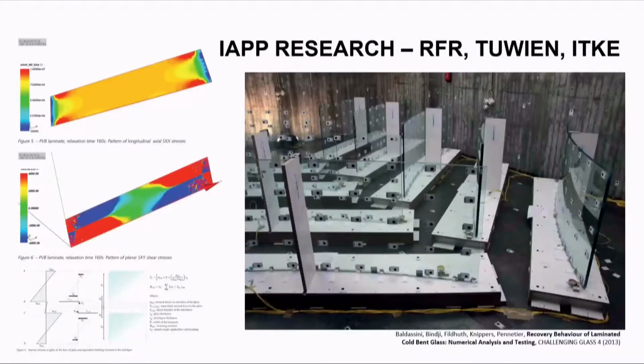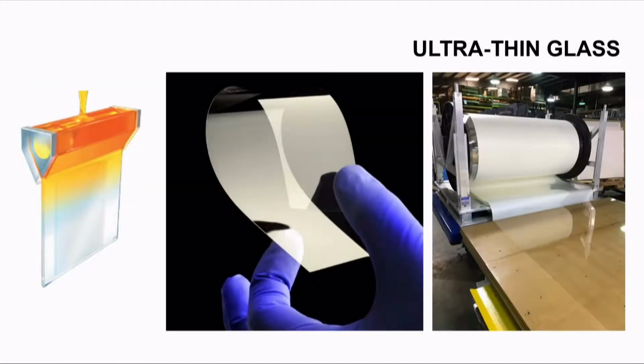And so at the time at RFR in France in 2010 and 11, I did some extensive research in cold bend glass, studying various laminate compositions, trying to understand how that shear basically creeps in time. But another thing that I realized at the time is the stiffer the compound or the thicker the glass, the bigger the force you have. So which means that if you want to lower the force on your supporting structure or minimize the spring back, well, then you should go for thinner glass. And this is what led me to actually stumble upon this ultra-thin glass product.